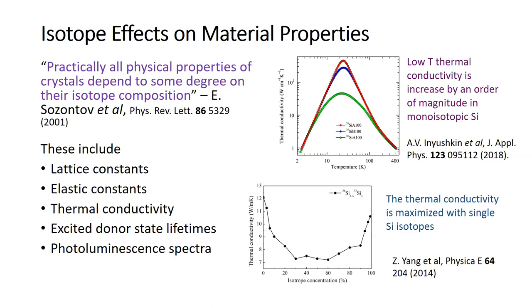And kind of what you would expect, as you mix the isotopes, with the maximum mixing at 50-50%, you see that the thermal conductivity goes to a minimum. This effect on thermal conductivity is due to isotopic disorder. Different masses will vibrate at different speeds, and so if you have two masses each vibrating at different speeds, they'll tend to scatter phonons more. So if you can eliminate that, you can increase the thermal conductivity and change some of the other properties as well. There are a couple other properties that vary with isotope concentration also.